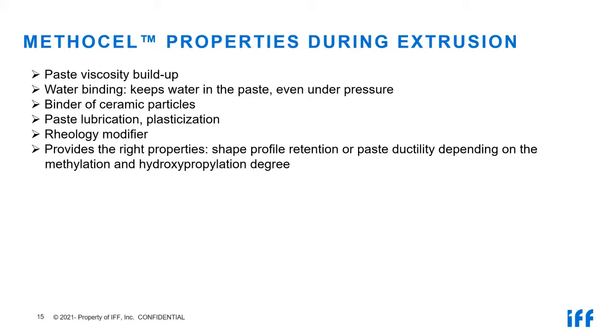If you ever have seen a water drop falling out of your machine, for instance, at a seal or some other parts, this can lead to extremely fast development of pressure and to a high danger for the machinery. Machineries, even with 1 centimeter thick steel, can break. And this is a question of the water retention capability of the cellulose ether, and definitely this is a contributor in such a problem. If you have ever seen such a problem, please immediately replace this cellulose ether or reformulate it.